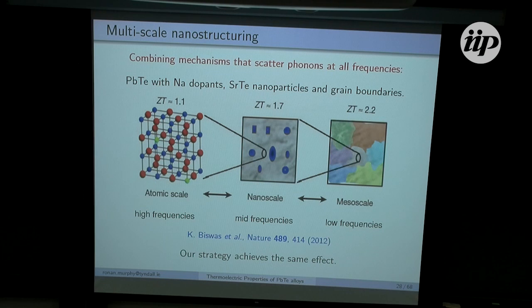Now, you'll probably recognize this picture. It's already been shown once already, but this is another approach to achieve the same effect. So in this case, in order to scatter phonons across the frequency spectrum, you introduce dopants on the atomic scale to scatter high frequency phonons, nanoparticles on the nanoscale to help scatter mid-frequency phonons, and then you introduce grain boundaries to target low-frequency phonons. And what our approach demonstrates is that by pushing lead telluride to the verge of the phase transition, you can achieve the same effect as this approach and scatter phonon lifetimes, particularly those low-frequency phonon lifetimes.